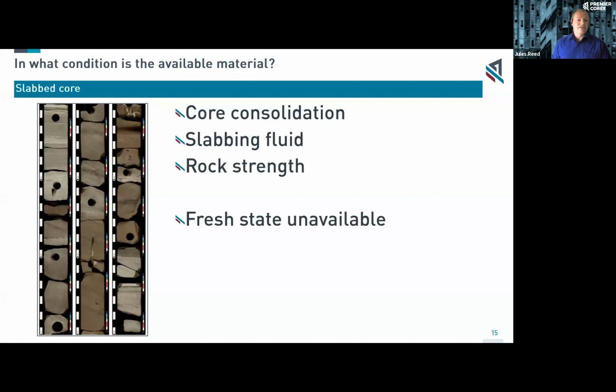There's also, over time, the fluids in this slab core will be evaporating. That could lead to salt precipitation, and depending on where it precipitates, could lead to weakening of the structure. And so you may end up with this slab core degrading in quality over time and over the number of years that it's stored. So one of the tests might be, as well as looking at standard properties, look at things like rock strength. Perform a UCS, or unconfined compressive strength, and check that you've got similar properties to the original core, if that data is available. And of course, again, on slabbed core, you cannot get fresh state analysis.